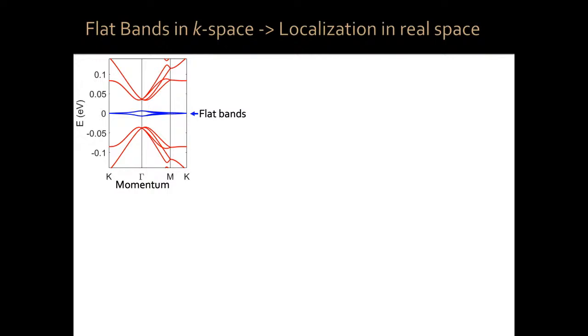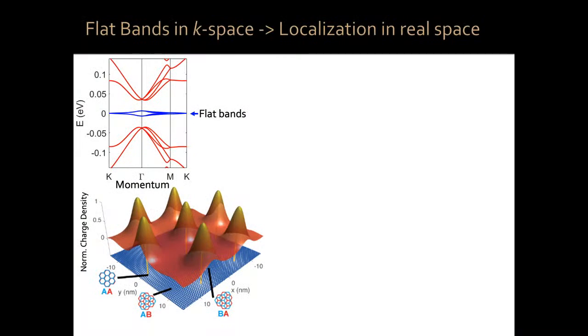As you can see, they are not perfectly flat. They have a little bit of dispersion, but this dispersion is orders of magnitude flatter than the original graphene dispersion, this Dirac cone. Now, flat in momentum space, if we want to look now at where are the electrons that sit in those flat bands in real space, you have to do a Fourier transform. Flat in momentum space means highly peaked in real space. So if you calculate where are the electrons in these flat bands, the electrons like to sit in certain regions where locally all of the carbon atoms are on top of each other.